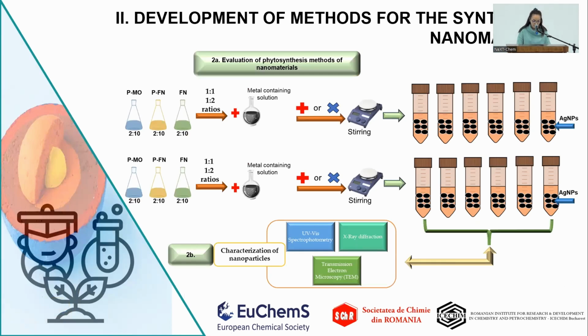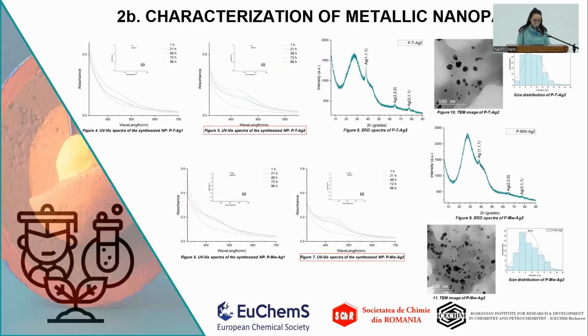The phytosynthesis methods of nanomaterials were evaluated, and to facilitate this process, the 6 extracts were combined with a metal-containing solution in 1:1 or 1:2 ratios, with or without stirring. And in order to obtain important information about their formation, nature, and structure, they have been characterized by different non-destructive techniques. So the first step carried out, in order to confirm and to follow the formation over time of the nanoparticles, consisted in the evaluation of the UV-Vis absorption spectra of the samples, which were measured at various time intervals in the wavelength range of 300 to 700 nanometers.